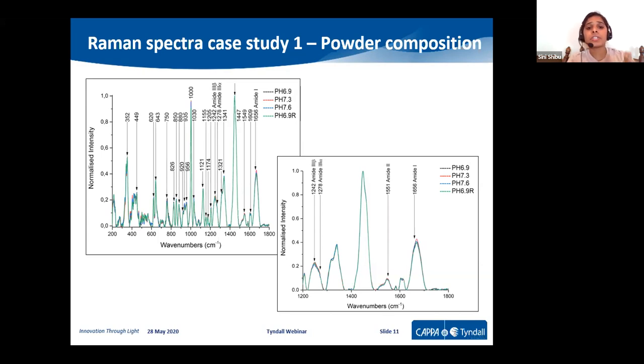According to their rehydration experiments, the pH 6.9 restored sample is showing very fast dispersibility and solubility compared to other samples. So we were also expecting, even in the Raman spectra, that we could see some difference in the amide or casein structures, because there is a very evident rehydration property difference. It should be seen in the Raman spectra also, but it was completely reversed to our expectations, because the Raman spectra in the 1200 to 1800 region shows no evident differences in the casein secondary structures in the casein proteins.